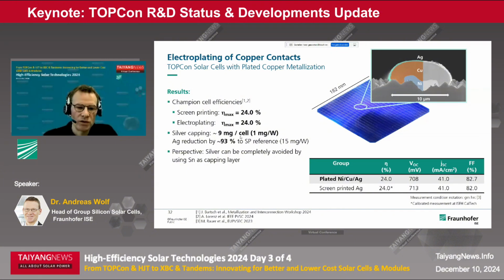And for these cells, we were able to demonstrate a very low silver consumption. And on the long term, we also are confident that plating cells would be able to be processed without any silver consumption.